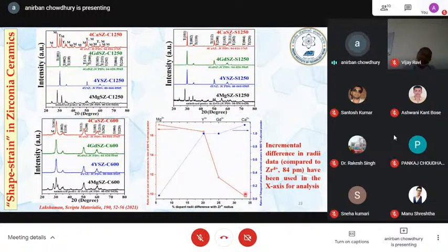And when you control this size in the sintered body, you can now improve the tetragonality. Magnesium has the lowest control. That's why magnesium has the lowest amount of the tetragonal phase developed. Once you have more control, when you can keep this size to a minimum, you can have the maximum amount of tetragonality. So this blue one is the ratio of tetragonal phase from the ceramic to the 600 degree C calcined powder. So you can see that now this is increased.